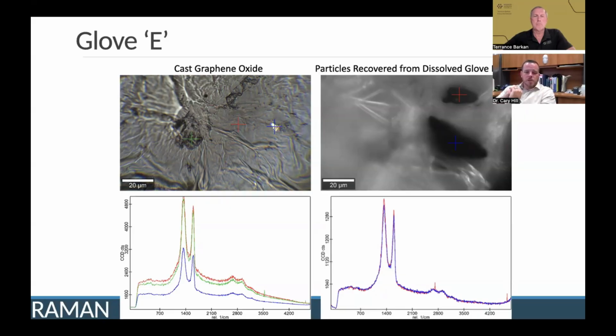So on the left side is just the graphene oxide material, the slurry that's used in the production process. And if you're familiar with Raman spectroscopy, you'll see that characteristic G and 2D, and then the double-mediated slopes of the 2D on the right-hand side of the spectra. And then we found the same signature, a matching signature, in the particles that were recovered from those dissolved glove fibers.